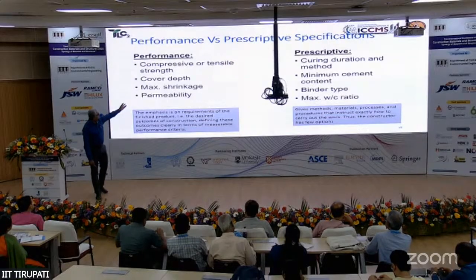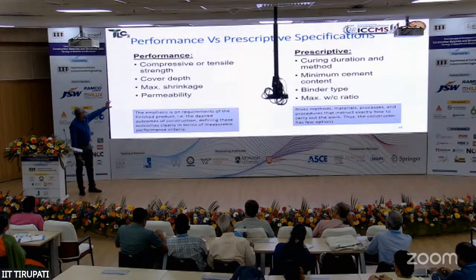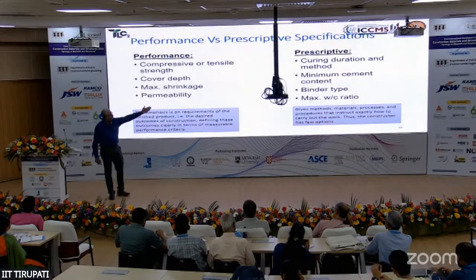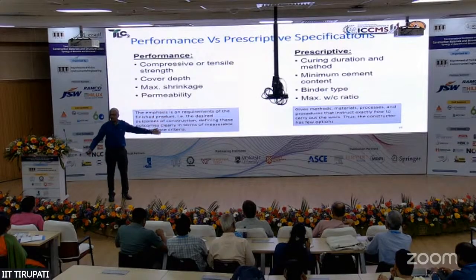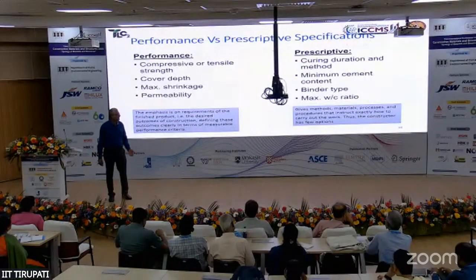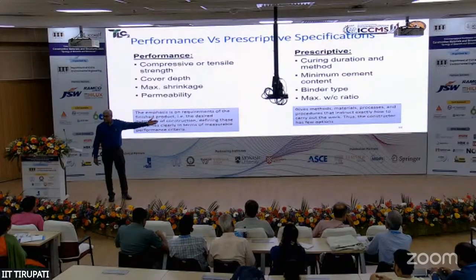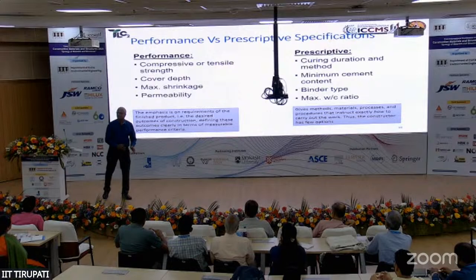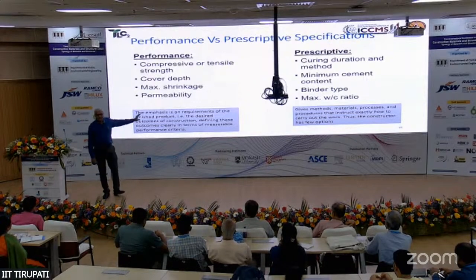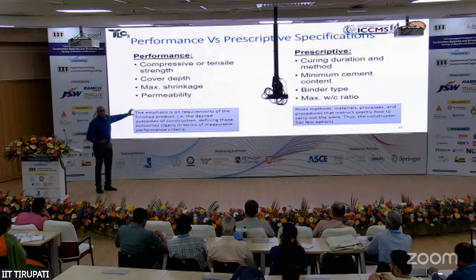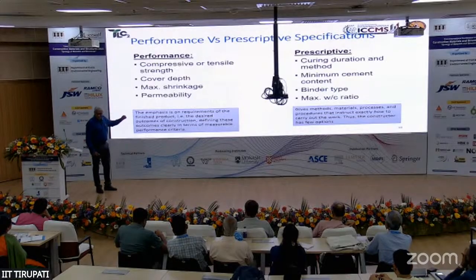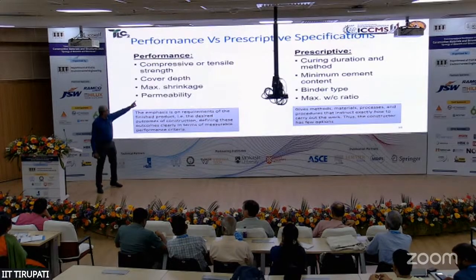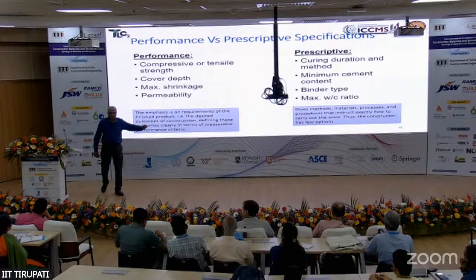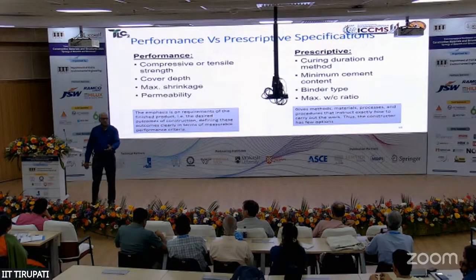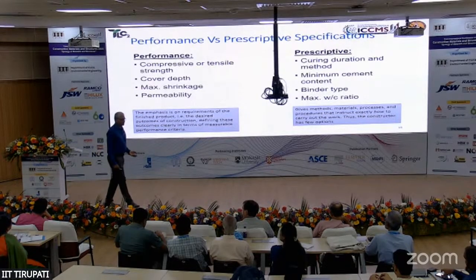So just to give you an example, of course, prescriptive specifications can include curing duration and method, say 7 days curing by water fogging or ponding or something like that, you say that minimum cement content should be so much, maximum water cement ratio should be so much, you have to use only this type of binder. Those are prescriptive specifications. A performance means you are having a measurable parameter that you're defining. Now, interestingly, in many of your specs, you would have already seen cover depth as a prescriptive spec. It'll say that for an extreme exposure environment, use 75 millimeters cover depth, right?